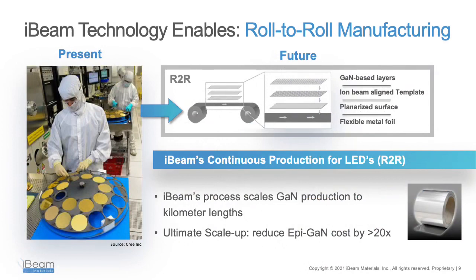In particular, depositing LEDs on inexpensive and flexible, robust metal foil enables roll-to-roll manufacturing of LEDs. Instead of using the single crystal wafers, as is done in industry today, the Ganox process can be scaled and automated to kilometer-long rolls of metal substrate. That is a scale up to 5 orders of magnitude larger than the wafers. And this reduces the cost ultimately by more than 20-fold. It also improves the deposition process as the substrate materials are better thermal conductors, leading to better wavelength uniformity of LEDs, among other things.